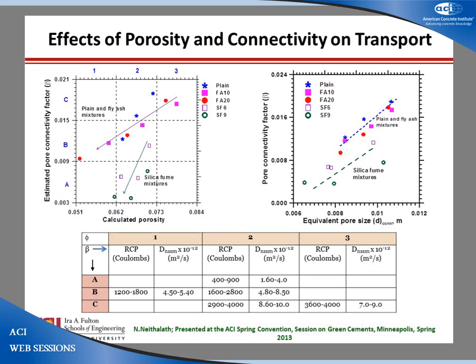So two or three different seemingly complicated things, but fairly simple at the end of the day if you think about connectivity being the determinant, and connectivity being determined more importantly by the sizes than by the porosity themselves, within the range of porosities. We're not talking about 60% porosity. The story will be different then. But what you see in normal concretes is that the size determines the connectivity more than the total volume of pores.